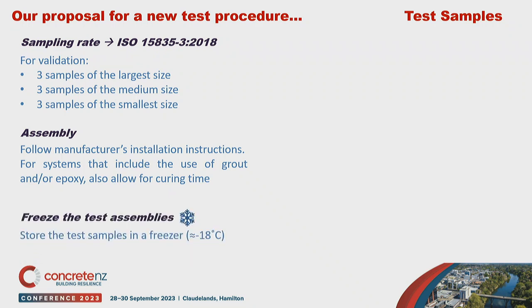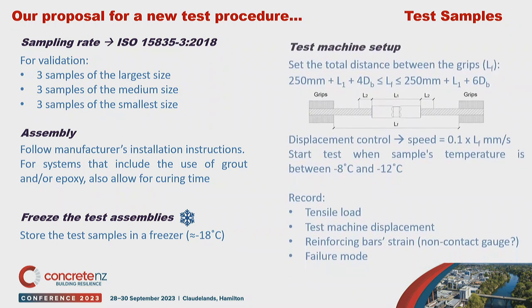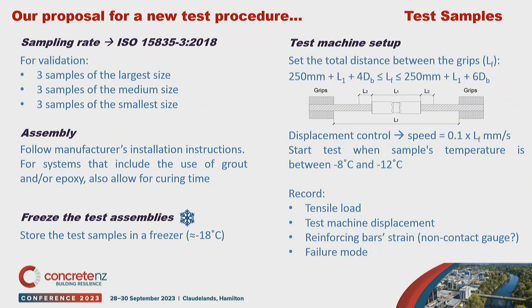We then freeze the test samples, get them a little bit colder than the target, so that when we put them in the test machine, they'll get a little bit warmer. We'll be monitoring that, of course. And then we obviously have to control the speed to what our target is. And this is where the longer specimen starts to come back and bite you, because your machine has to achieve 10% in one second of that length. So for a 250 mm specimen, that's 25 mm a second. That's reasonable. But if you go longer, obviously that increases. So, challenge.